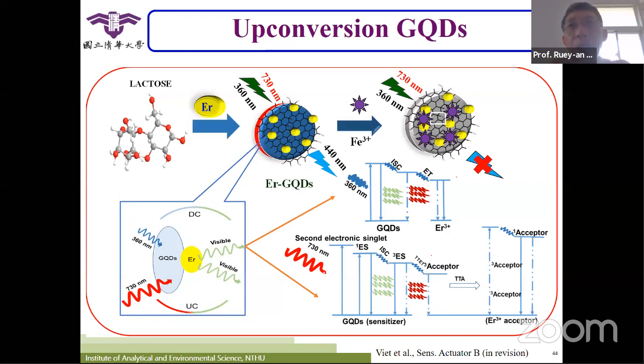Just think about solar energy. For solar energy, people would like to use visible light, even the IR region, so that they can enhance light penetration and light harvesting efficiency. But it seems quite hard at this moment to use the long visible light and near-IR range. So if you add the upconversion GQD inside, they can use long visible light of 730 or even 900 nanometers. They can recover the low-energy light, and your solar energy conversion becomes more efficient. So that is the case. We try to develop upconversion for GQD.